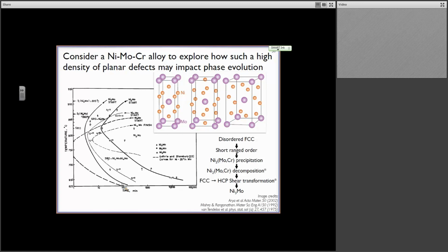That second phase isn't necessarily the equilibrium phase. The second phase that we want is actually this one right here, which is a metastable precipitate that has a structure of Ni2(Mo,Cr) like this. And if we want to get that, we take our alloy, we anneal it, and then we do a heat treatment down here for about 24 to 72 hours around 650 C, and we just cross this line and start to develop this precipitate structure, which has implications for the strengthening mechanisms and so on and so forth.